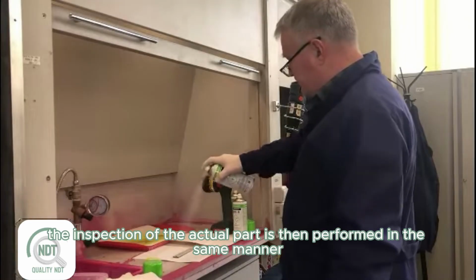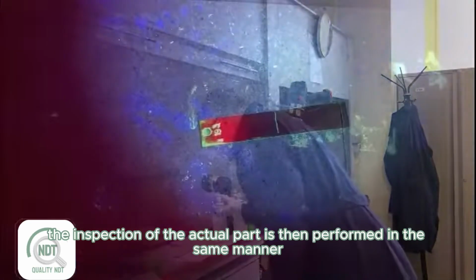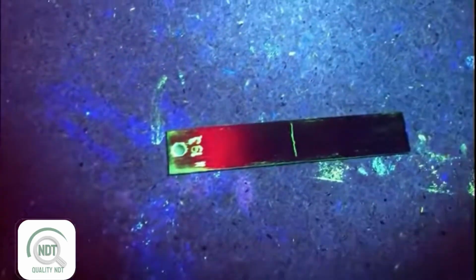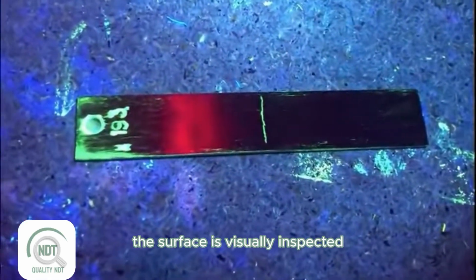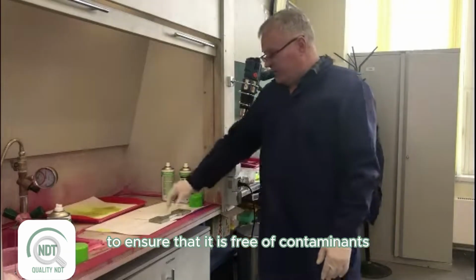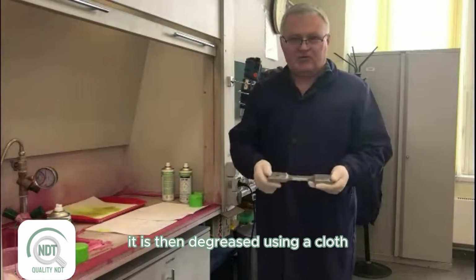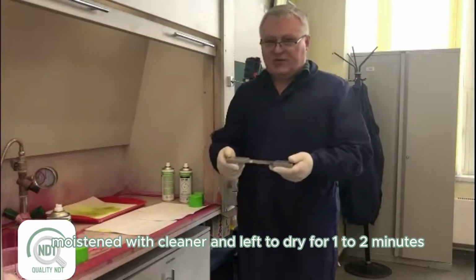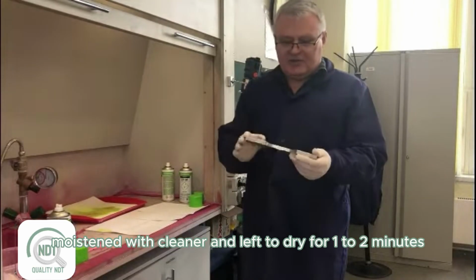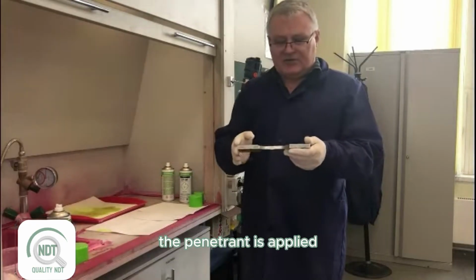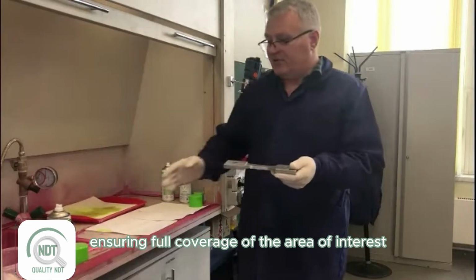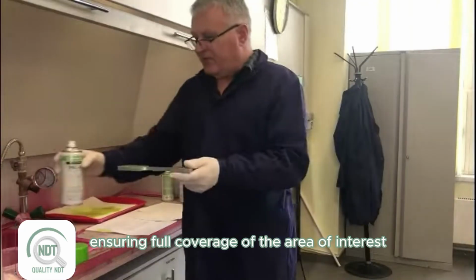The inspection of the actual part is then performed in the same manner. The surface is visually inspected to ensure that it is free of contaminants. It is then degreased using a cloth moistened with cleaner and left to dry for 1 to 2 minutes. The penetrant is applied, ensuring full coverage of the area of interest.